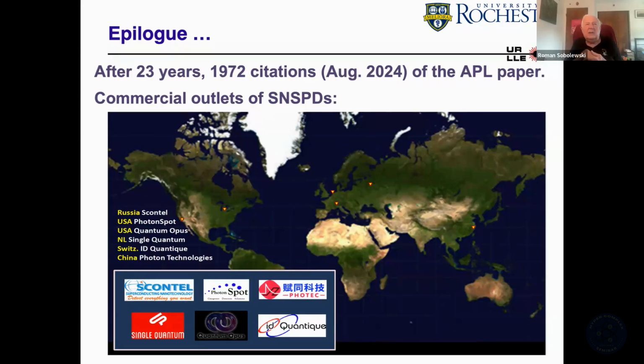It's a fabrication issue because the coherence length is on the order of nanometers, and that makes the hotspot size on the order of nanometers. So the line would need to be a few nanometers wide, and the technology is still not there. People cannot fabricate ultra-thin, ultra-narrow YBCO films while retaining a 90 or 93 Kelvin critical temperature. And from an application point of view, if you buy a cryocooler, it's a question of money. You don't need to go into liquid nitrogen.